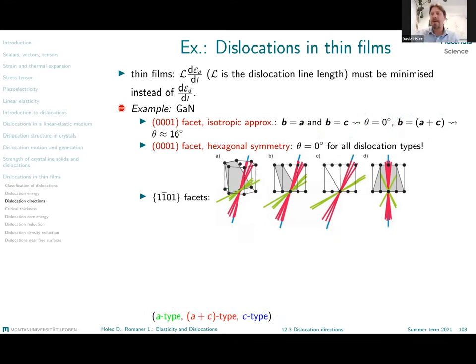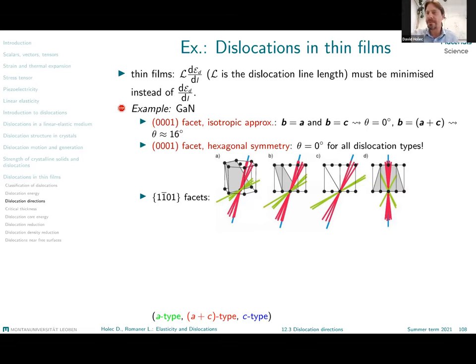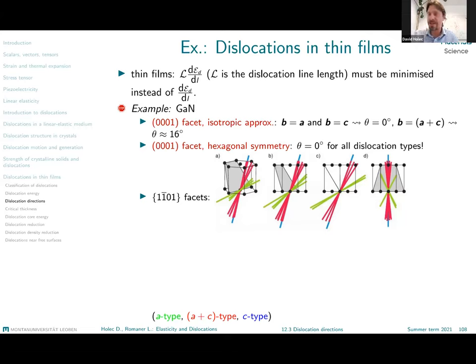So we get here an even more confusing result saying that for a certain geometrical configuration, edge type dislocation minimizes the overall energy of the system. Things might become more involved when we consider different orientations of the interface. Hexagonal gallium nitride can be grown on very different substrates, enforcing that the vertical direction has different configurations. For example, for the prismatic plane 1-bar 1 0 1, none of the A plus C or C type dislocations is perpendicular to the interface, and even the A type dislocations would have a certain slight preferred spread of their directions.